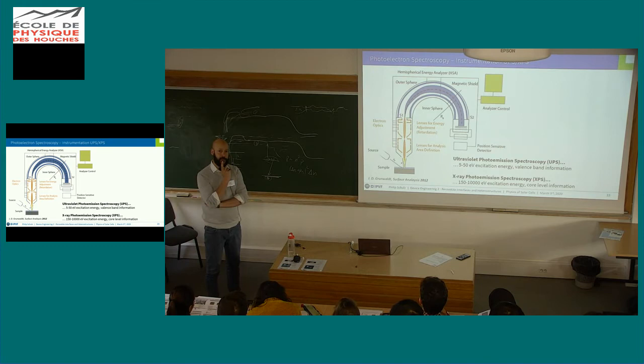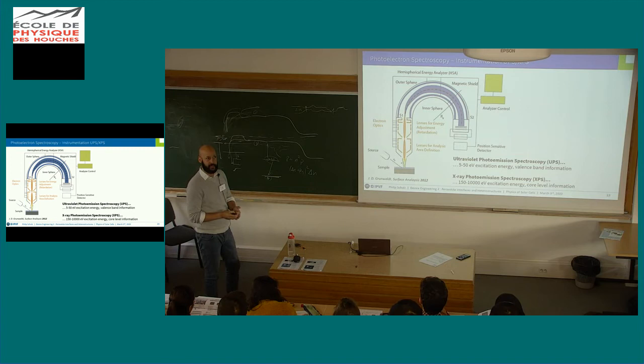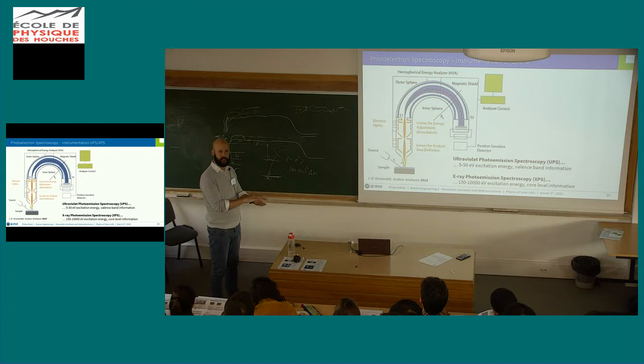so it's difficult because depending on the voltage, the pass energy of the analyzer changes, which means if you're operating at high voltages, you only let through high kinetic energy electrons. And these give you a smaller yield. So if you're operating at low energies, you get a lot of electrons through this, whereas at high energies, you get only few through it. Excuse me, it's the other way around. So at low pass energies, you have more probability for the electrons to actually be filtered out. So at low pass energies, you have a very small yield, and at high energies, you're actually collecting a lot, but the accuracy of the system becomes smaller because they reside for a shorter period of time in this electric field.